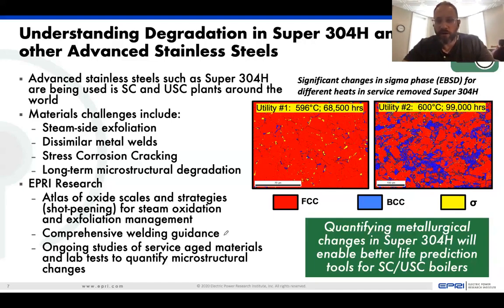And these materials need to be understood in light of challenges that have been encountered in many plants around the globe with steam side oxidation, the failure of dissimilar metal welds, out of service stress corrosion cracking, and then as we're showing in this image here, long-term microstructural degradation. And it shows the complexity of the structures and the formation of deleterious phases. In this case, these small little yellow dots that you may see, or these blue regions that you may see in these images, represent phases which form only after long-term service exposure and how they affect properties. So we build up tools like our Atlas of Oxide scales and our welding guides, and we use this fundamental data to inform life management decision-making.